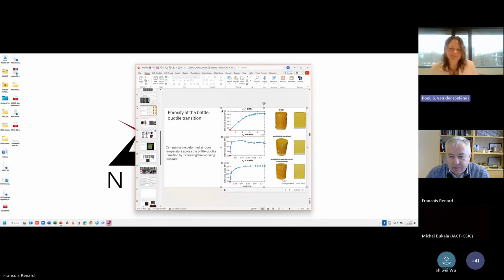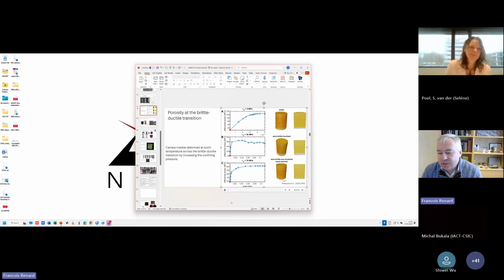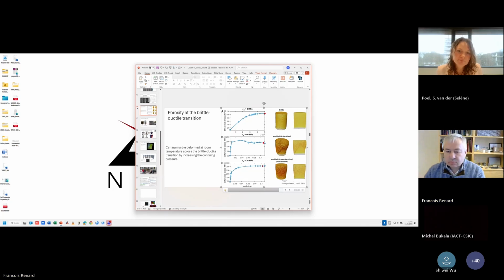Yeah. So okay. When you do this experiment, you have to design how you load a sample, so the rate at which you load is compatible with the rate it takes to get a 3D scan. So for these 3D scans, to give you the entire experiment, each of them lasts between 8 and 10 hours. We have perhaps 100 scans acquired, and each scan is 3 minutes. And I just show here only a few of them because we don't use all the scans.